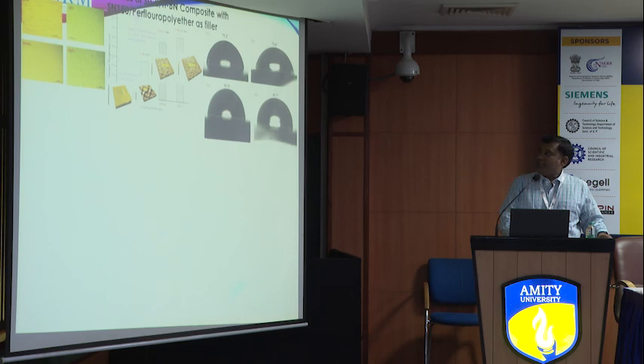And we also checked the surface roughness by atomic force microscopy. After adding the filler, what we have seen is that nanotextures are formed. You can see clearly the nanotextures, which are very small, formed over the surface. And due to these nanotextures the wettability is changed: pure SU8 has a hydrophilic nature. Hydrophilic means your water contact angle is less than 90 degrees. Hydrophobic means your water contact angle is greater than 90 degrees. Because of the addition of the filler, this surface becomes hydrophobic, and you can see here we get approximately 95.7 degrees. That was hydrophobic in nature.